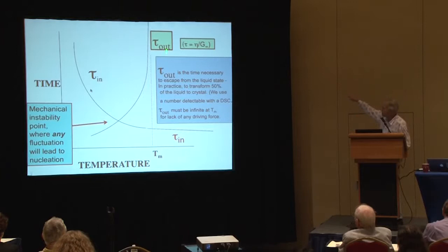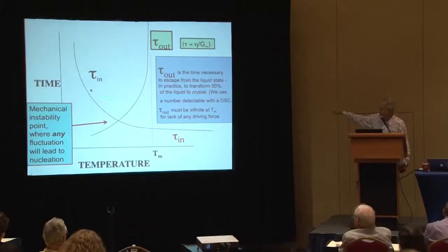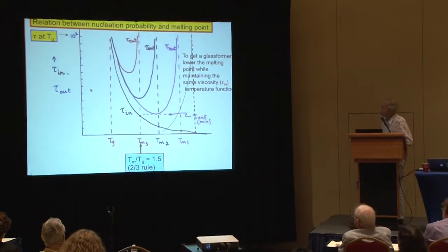And if it was just like this, then at this point here, as Valeria's more or less indicated for the MW model of water, there's a time scale crossing. And under that condition, at any lower temperature, the system has to crystallize, because any fluctuation will take you into the crystalline state. There's no way out of it. And if you're going to get a glass, something has to be changed about this diagram. So here's what, and this is, sometimes you get attached to a diagram.